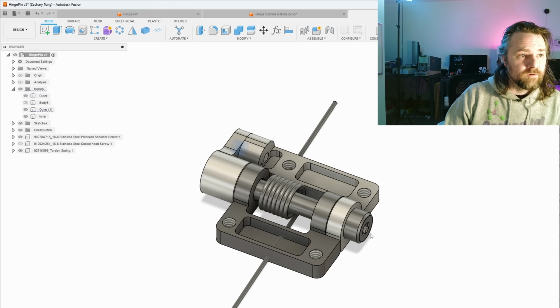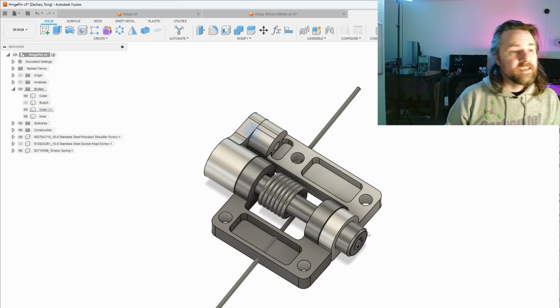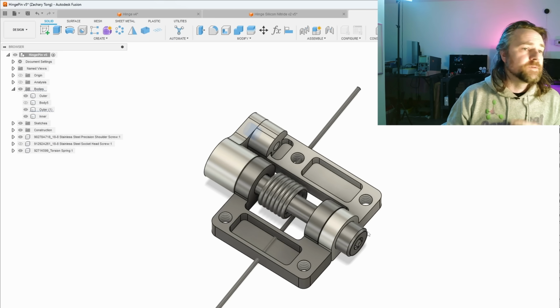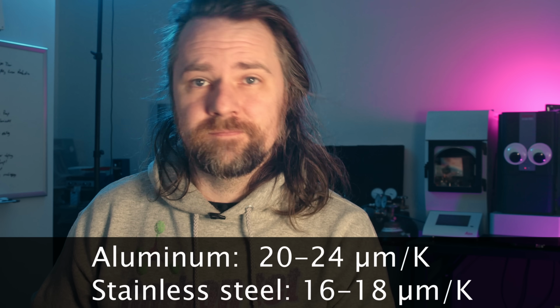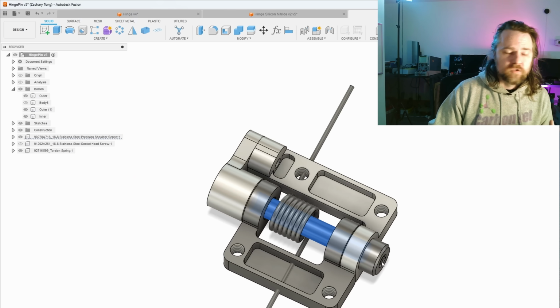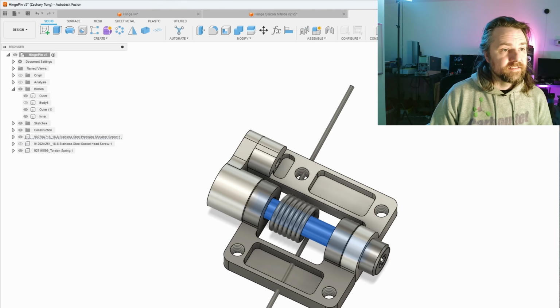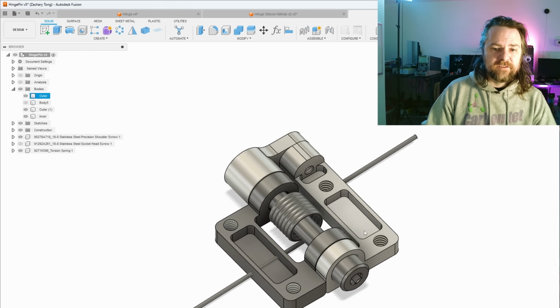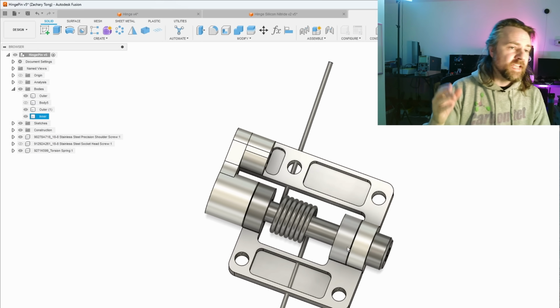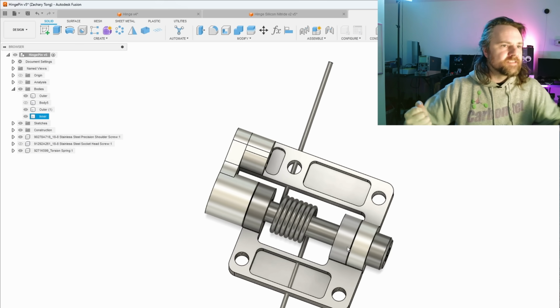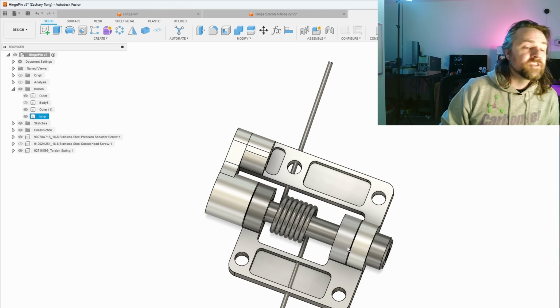Unfortunately, there's a bigger flaw to this design, which I didn't think about at the time, but potentially could be catastrophic to a mission. And it's again related to the materials that are used here. The shoulder bolt is steel and the hinge is aluminum, and now we have a thermal mismatch between the two materials. The thermal coefficient of expansion for aluminum is about 2 times that of steel, or stainless steel in our case, meaning that as the temperature rises, the aluminum part of this hinge will grow twice as quickly as the steel parts. So for example, if the steel bolt grows 20 microns, the aluminum is growing 40 microns. And if we don't have our tolerances sufficient to compensate for that, we could get into a situation where the inner or the outer half of the hinge expands enough that it pushes on the shoulder bolt and finds itself in a position that can't open once we get on orbit.